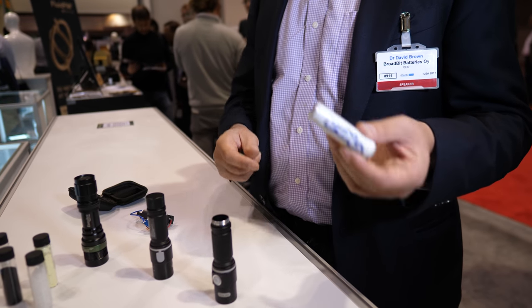Is this really going to be twice as good as lithium ion? So right now this is the first generation — our Gen 1 cell — and this is about 300 watt hours per kilogram when we're in production. We're also working on the next generation, which should be above 400 watt hours per kilogram. Right now these are handmade, so they're not that good yet — about 100 watt hours per kilogram handmade. The very best lithium ions today are around 250, and a typical one is around 150. So at the coin cell level, if you add all the layers in their optimal ratio, we're already better.